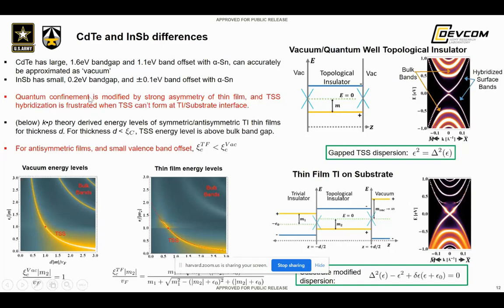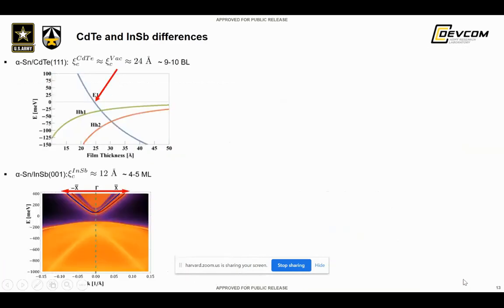This makes it, and one can show in essence, that the critical thicknesses are affected by the fact that you don't get formation of a topological surface state at the bottom surface of the material. And this is expressed by this theorem, that typically the critical thicknesses are smaller than what you would expect if you assume a vacuum approximation for the material. And this is a little clearer if one points to the next slide.